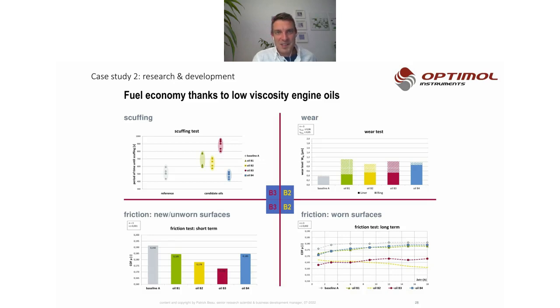It's very easy to read, because on the left side you will see the results of your reference. That's the actual design. Then you can compare to the other candidates, for example, those 4 combinations, and you will see the higher the points, the higher the resistance against scuffing. You will have a clear understanding that the red candidate is the best because it's the most robust solution. But it is also suitable to use the green, the yellow one, or even the blue one, but it's way on the bottom, and it's not better than your reference.